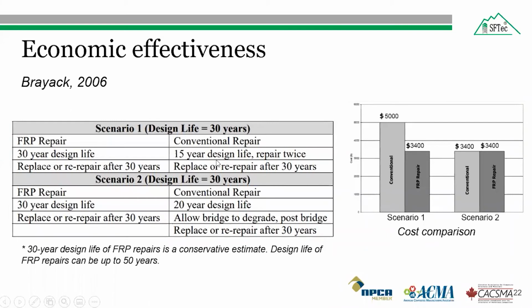So for the conventional method, the present worth cost of the first scenario was $5,000, compared to $3,400 for FRP repair, which is much higher because in the conventional method we have to repair the structure 2 times. But in scenario 2, a present worth analysis does not apply because it doesn't include a future repair. So here we can see that the FRP repair improved the design life without increasing the cost of the structure.